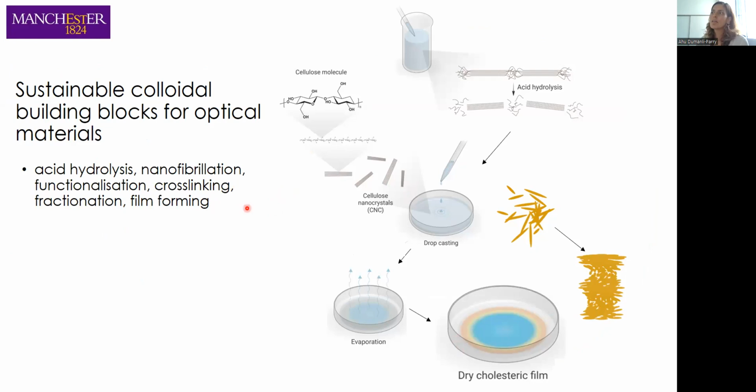So for us, we work with cellulose a lot, but we also work with chitin as well. And when you look at the structure of cellulose, we see that there is this fibrillar component which is coming together. Polymers are coming together to make fibers, but these fibers are not organized all the way through. They have very organized crystalline parts as well as amorphous parts to balance between strength of the material as well as the flexibility. So the mechanical strength is optimized this way.